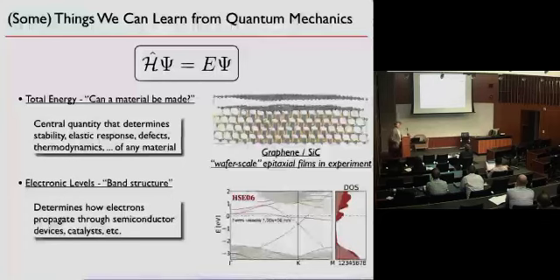Now what we could show with very similar calculations as I talked about was that there's actually a narrow range of equilibrium conditions where this material grows on its own. So if you heat to the right temperature and have the right silicon background pressure, ideally this material should form, and that's how it's made in experiment. Okay, that's good. We should have been there 10 years earlier, because experimental groups figured out the recipe on their own, although I doubt anybody was able to prove it's an equilibrium phase.